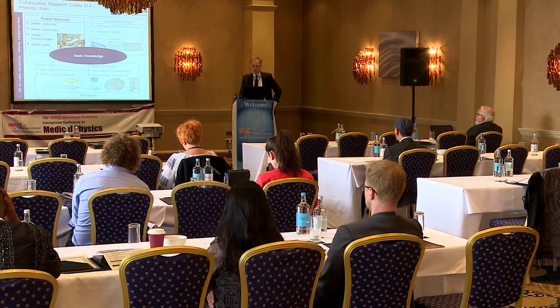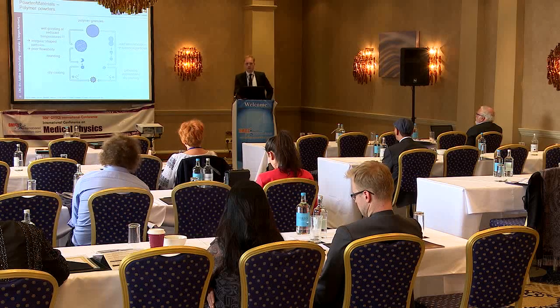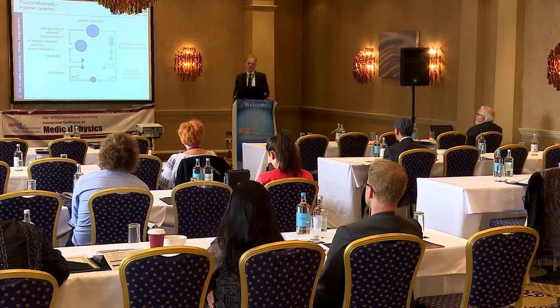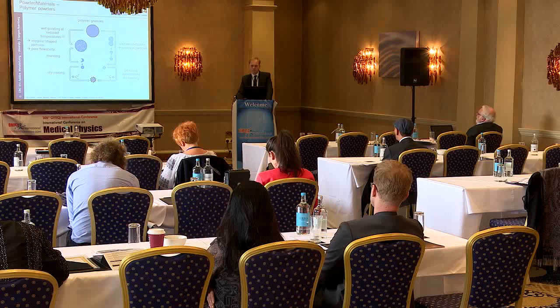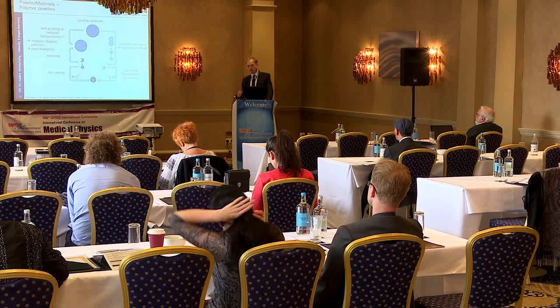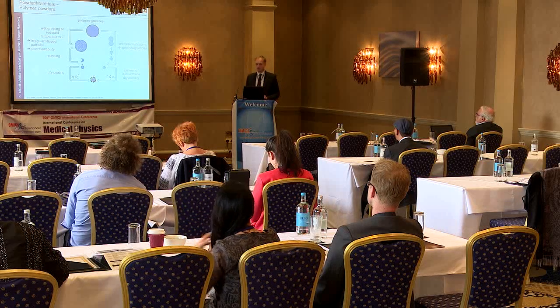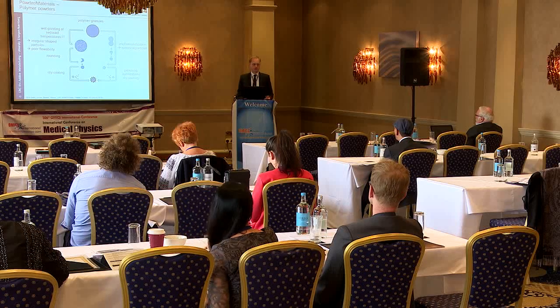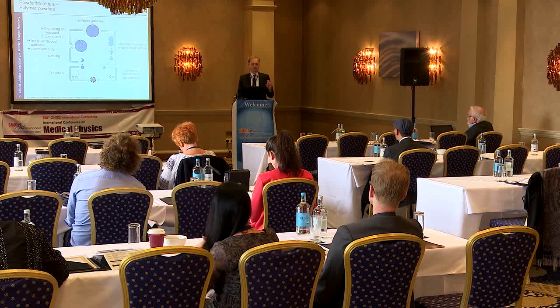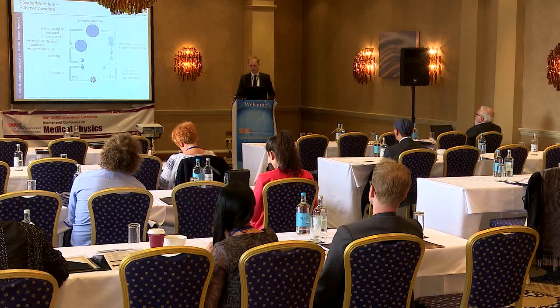And I will start with the powder materials, and I will focus on polymer materials, because polymers are quite difficult to get into a powder stage. They have problems with the surface tension, and sometimes they are not brittle enough. For metals, these problems aren't as significant. Metals have a very good surface tension. They have this balling effect, and if you have a melt and give a gas into it, and then you have a spray, the metals ball really well, and you get round spherical powders.